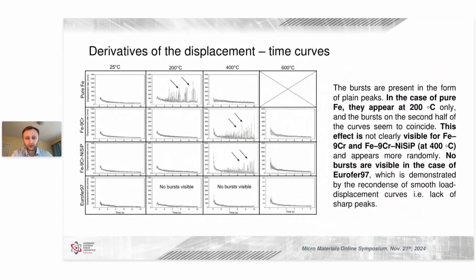So to understand a little bit better the origin and the magnitude of those steps, we plotted derivatives of the displacement time curves, and yet again we saw that these bursts, as we call them in our work, appear only at 200 degrees on iron, and we see them at 400 degrees when we test iron with chromium and iron chromium with solid atoms. Although at 400 for the iron chromium with solid atoms material, the magnitude of those bursts is much lower, and they do not appear in Eurofer 97. So what is really going on?